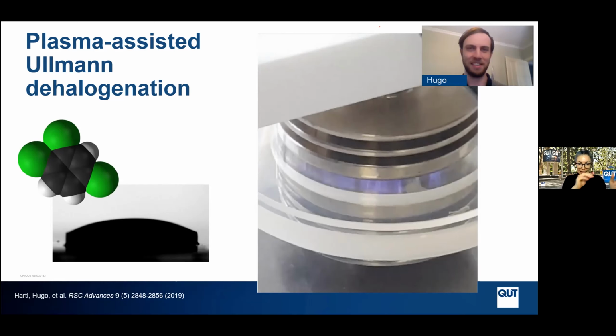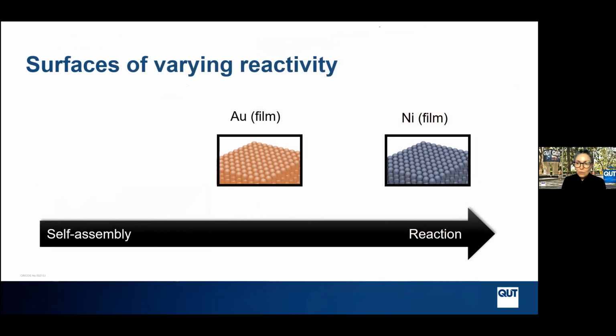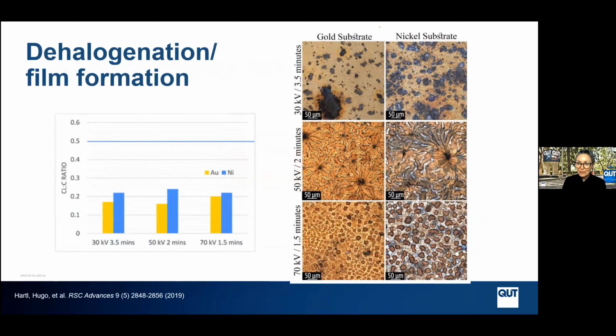So the side view that you're looking at there is actually just the liquid droplet of the trichlorobenzene on our substrate. So the work that Hugo did started out with films. So we deposited films onto silicon and then looked at treatment with plasma to see whether we could achieve dehalogenation. We could. As it turned out, the dielectric barrier discharge plasma created this liquid to solid conversion, so we could visually see that the reaction was progressing. What you're seeing at right here, these are optical profilometer images that show you the types of structures that emerged after different treatment doses, essentially, in the dielectric barrier discharge plasma. The center ones are perhaps most representative. We get these sort of spinodal features, absolutely stunning at different length scales.